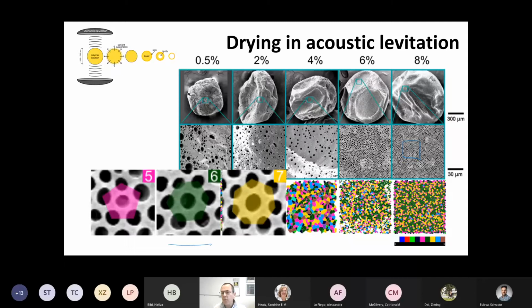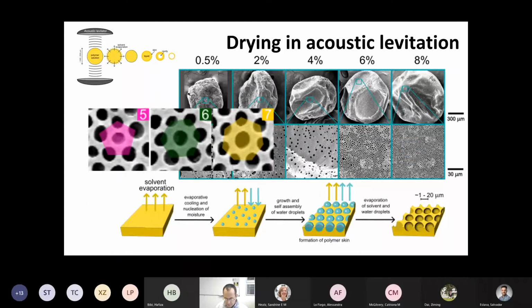And these are not even the most regular that one can access. These are called breath figures. And it's the kind of thing that you would obtain whenever you have a liquid that is evaporating, and upon this kind of evaporative cooling, you can get the deposition of water droplets, and in a nutshell, this is what you get: the evaporation of water droplets onto a skin that is becoming solid creates some kind of interesting convection currents that result primarily in this kind of hexagonal array.